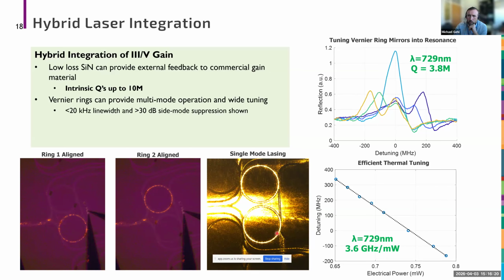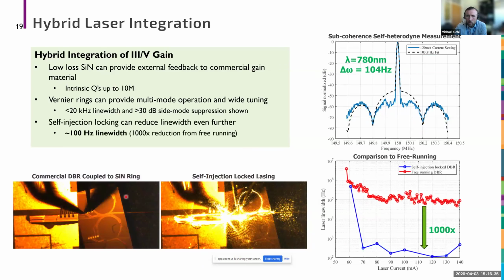And so this example here I'm showing is using 2 rings in a vernier mirror type configuration where we've shown that we can get the laser line width down to about 20 kilohertz. And then if we instead do a self-injection locking technique, which is what I'm showing here, we've been able to show as low as about 100 hertz line width, or a 1,000 times reduction in the line width of the free running laser.